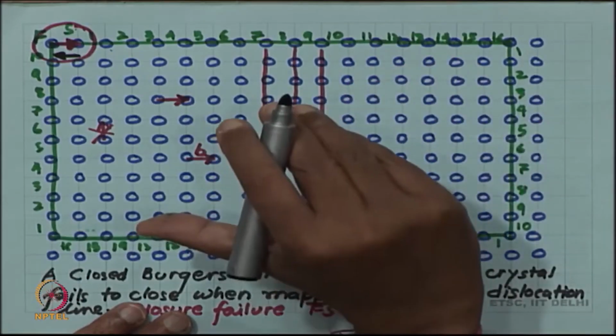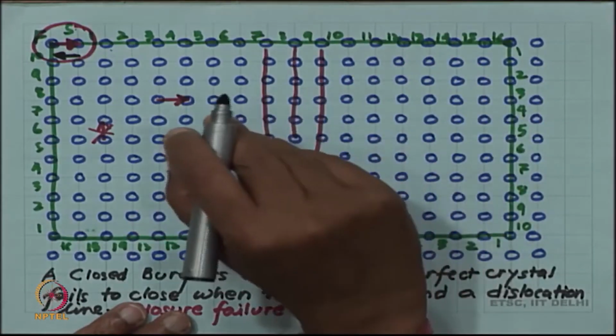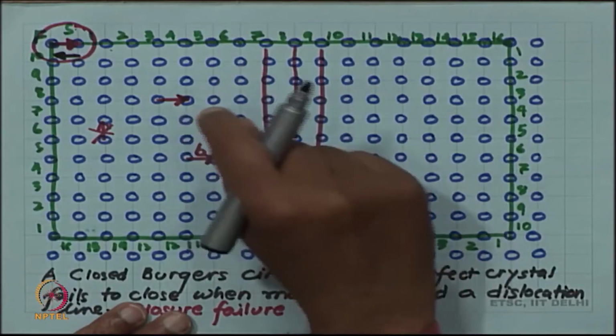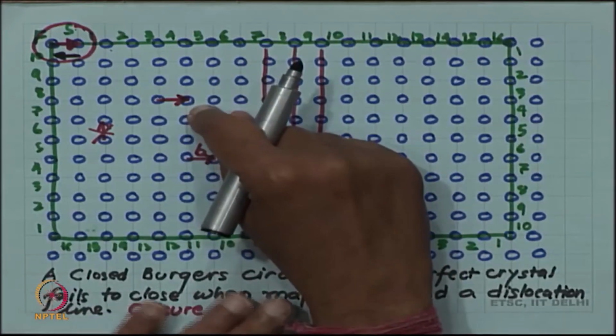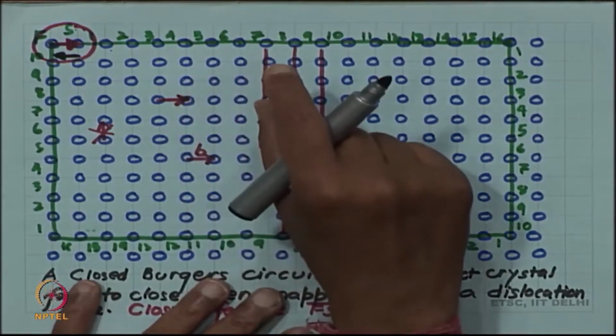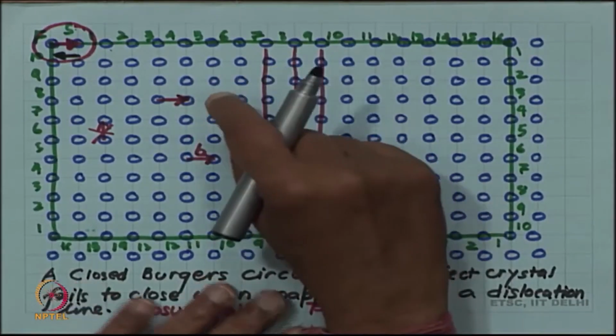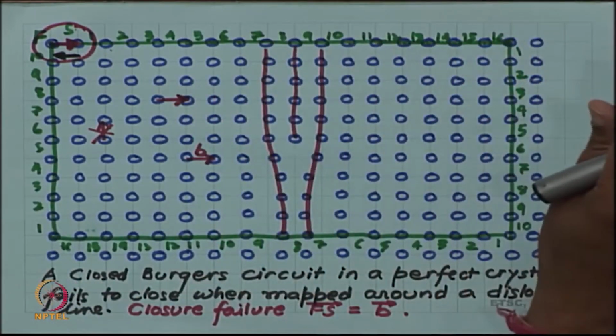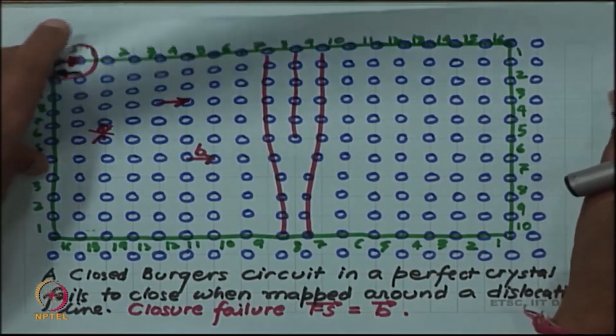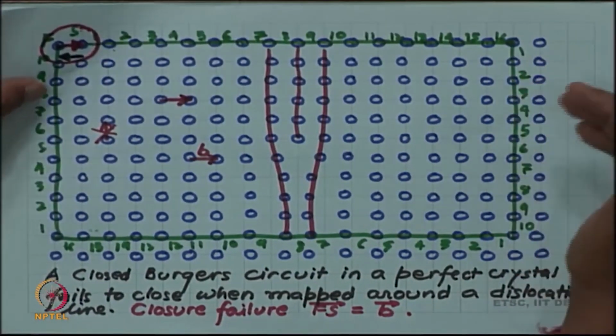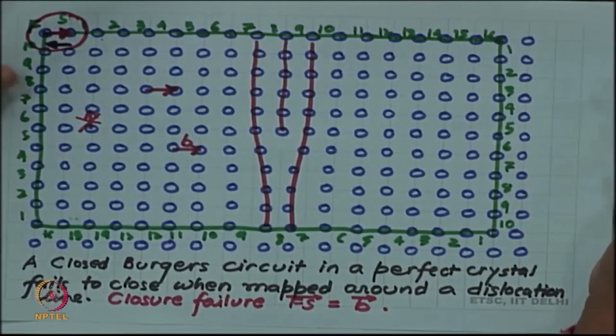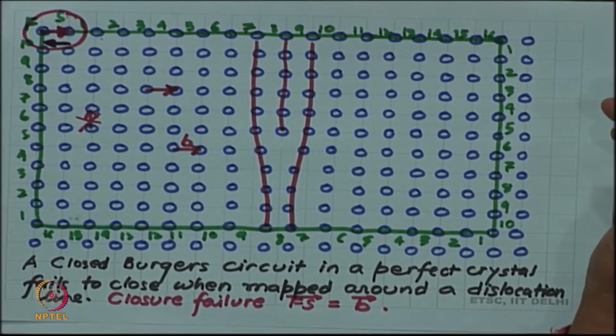If we look at the motion of the lower part, that will be in the opposite direction. So, the Burgers vector has a fixed magnitude and direction, but the sense can be either one way or the other. This ambiguity is always there, and to avoid it in any one discussion or in one piece of literature, one defines what is called the Burgers vector convention.